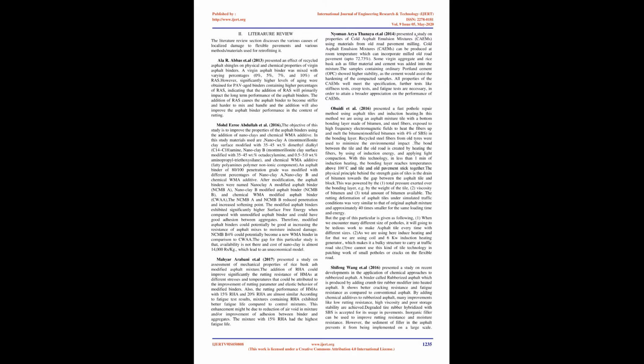2013, presented the effect of recycled asphalt shingles on physical and chemical properties of virgin asphalt binders. A virgin asphalt binder was mixed with varying percentages, 0%, 5%, 7%, and 10%, of RAS. However, significantly higher levels of aging were obtained for PAV-aged binders containing higher percentages of RAS, indicating that the addition of RAS will primarily impact the long-term performance of the asphalt binders. The addition of RAS causes the asphalt binder to become stiffer and harder to mix and handle, and the addition will also improve the asphalt binder performance in the context of rutting.